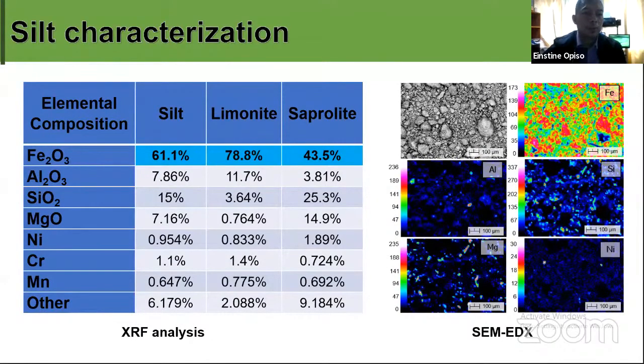For the elemental composition, our silt is composed mainly of around 60% iron in terms of oxides based on our XRF analysis. And this result corroborated with the results of our elemental mapping using the SEM EDX analysis. We also collected samples of limonite and saprolite from the mining company, and the iron contents are comparable with our silt samples.